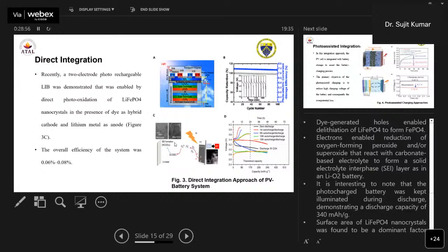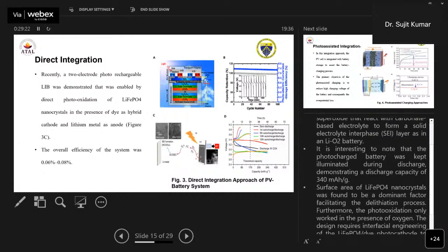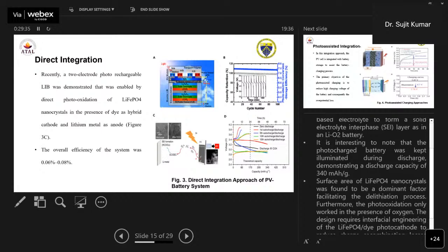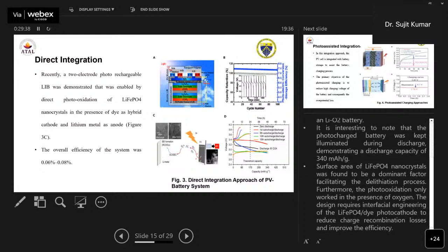One interesting note was that the photo charged battery was kept open, or you can say that it was getting illumination during the discharging process also. So when discharging, they have demonstrated a discharge capacity of 340 milliampere hours per gram. So the surface area of the lithium iron phosphate nanocrystal was found to be the dominant factor facilitating the delithiation process. And further, they have shown that this particular photo oxidation only worked in the presence of oxygen.